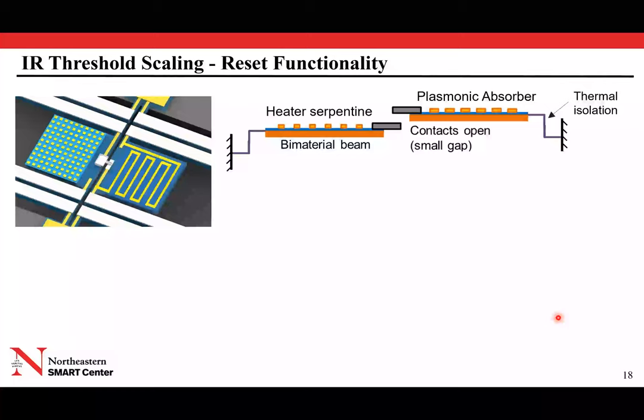So actually, we knew that when we started the program, and that's why we use a platinum contact, because it's been studied before, platinum is a good material for low adhesion forces. And in fact, I think we measured adhesion forces in our contact that are in the range of 10 nanonewton, which is pretty low. But we quickly realized that actually was not such a big deal. So if we could design switches that latch on upon detection, the only thing we need to do is to find a way to reset the switch after detection, right? Remember, these are very rare events, so it's okay if we spend a little bit of energy to reset the switch after detection.